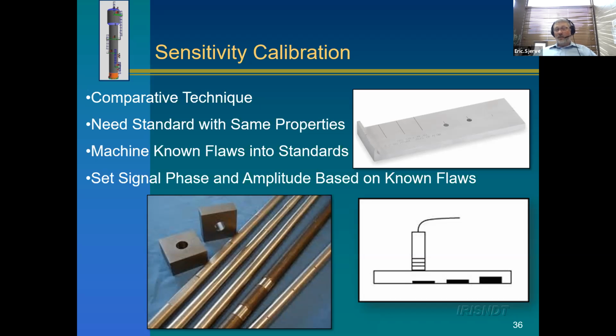And then when we go into an inspection in a heat exchanger, what we're doing is we're comparing signals from that heat exchanger to that artificial calibration standard. So that's how we're calibrating eddy current. And that's a bit different than the other techniques because it's not an absolute calibration. It's strictly a relative calibration where if we don't get that calibration piece correct, nothing is correct. So it's really important to have the right calibration piece with the right heat treat properties, the right metallurgy, the right diameter, thickness, and everything. If you don't do that, the whole inspection is flawed.